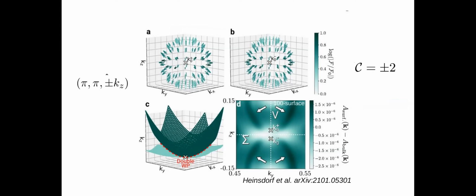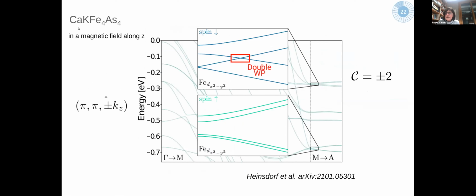For instance, I'm curious on the spin fluctuation. What would you expect the spin fluctuation will respond? Yeah. Okay. So this system, and in fact, this is an ingredient I didn't talk about. This system we know that, in fact, when you electron dope it, it shows this order, this spin vortex order. So we know that and there are, in fact, for this material, NMR data that show these spin fluctuations that come from vortex type of fluctuations. So what we expect is that these vortex fluctuations are also going to influence the presence of this type of Weyl points. Is this the question you are posing?